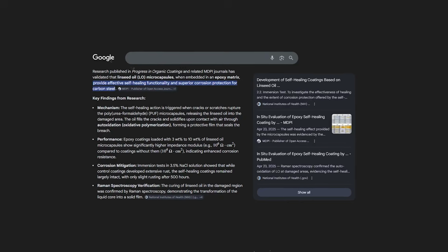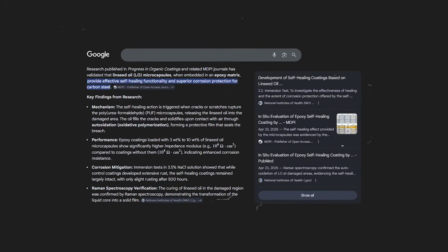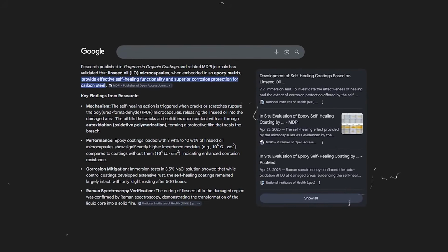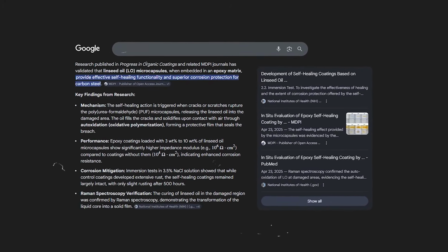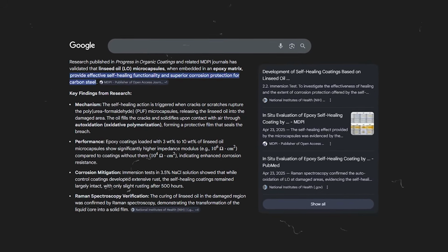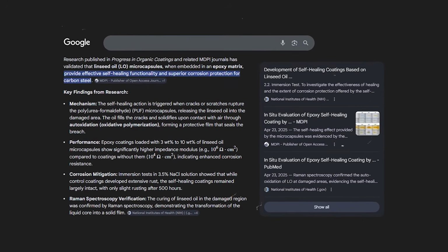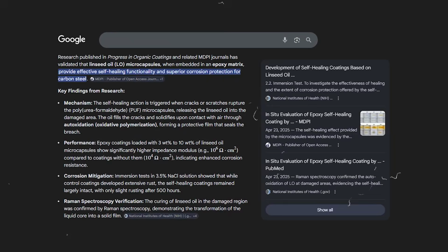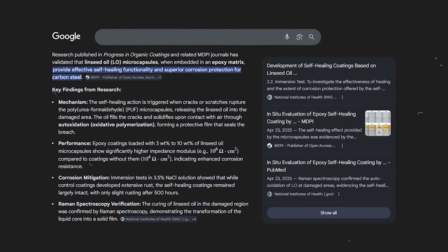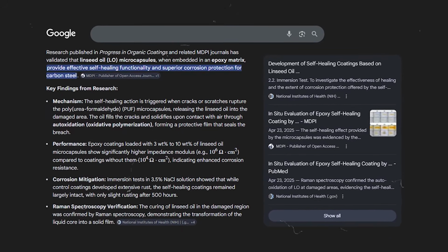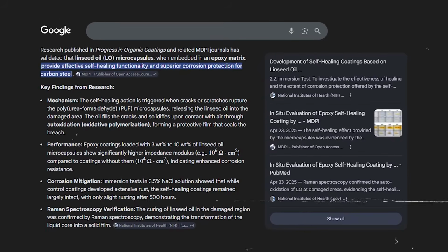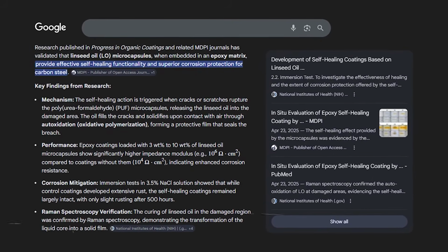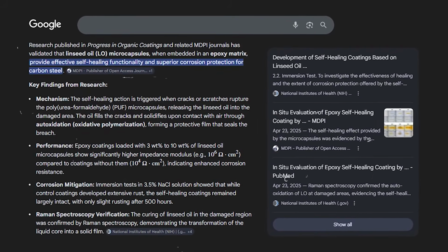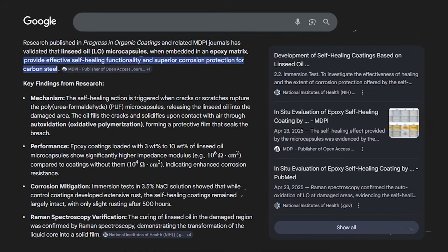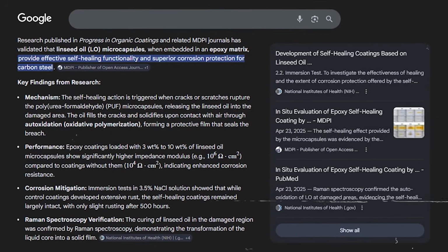Modern science has confirmed the effectiveness. Research on self-healing coatings, published in Progress in Organic Coatings, demonstrated that linseed oil microcapsules embedded in epoxy resin provided superior corrosion protection for carbon steel. The linseed oil released upon damage to the coating surface polymerized on contact with air, sealing the breach. The researchers were, in effect, trying to automate what a medieval blacksmith did by hand with a rag.